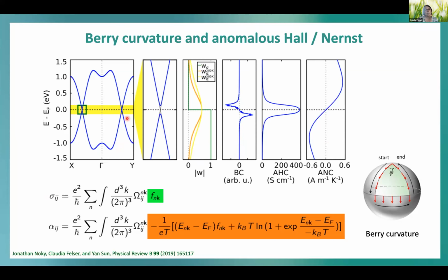We can also do a toy model calculation. This was the first step, and it shows that if you have crossing points at the Fermi energy and apply a magnetic field, the Berry curvature is enhanced around the Fermi energy.